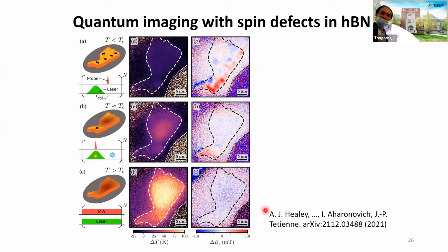There's another work where they use hBN for temperature sensing besides magnetic field sensing. Basically they have a flake and use a laser to heat up some magnetic material, so the temperature changes. What's remarkable is they can control the width of the laser pulse. With that they show that the spin defects in hBN can measure the temperature change within 100 nanoseconds. So it has a very fast time response. You cannot do this with diamond emission, because... Because of the thermal conductivity? Yeah, first of all, the material is very thin, so there's little thermal buffer. I see, the heat capacity is tiny. So it basically changes the temperature immediately.